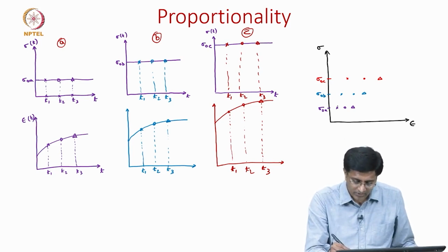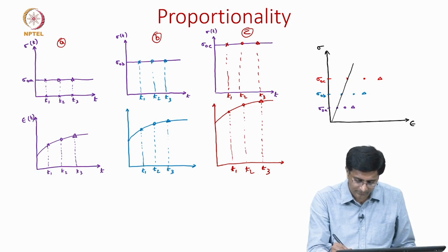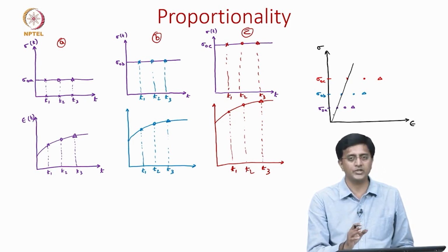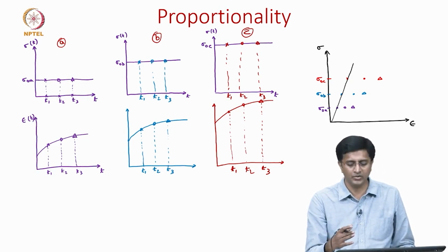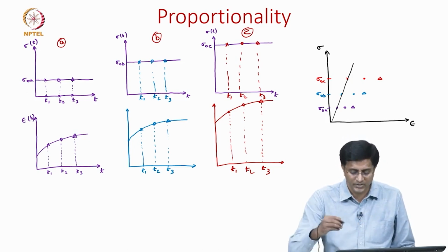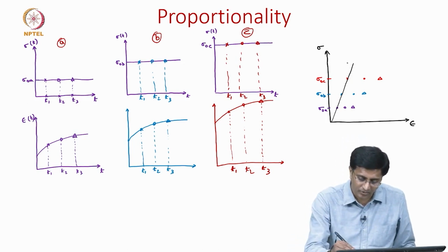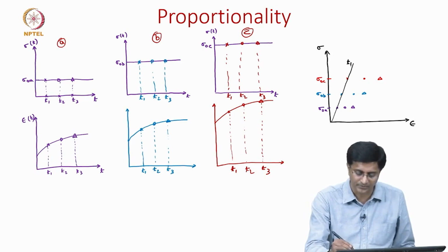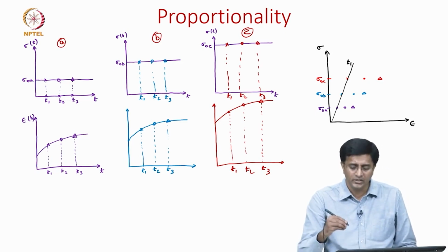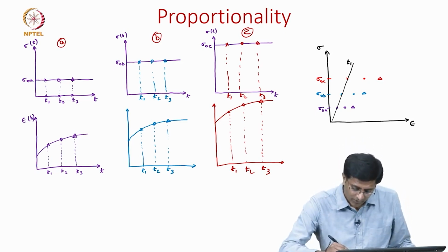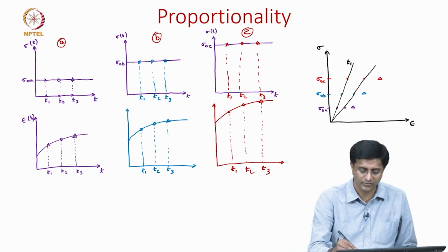So we have these 3 plots and if we connect them they more or less fall into a straight line. If they fall into a straight line, then we can conclude that at time t1 the response is linear. Similarly for time t2, we again see that there is linearity between the responses at the 3 different loads.